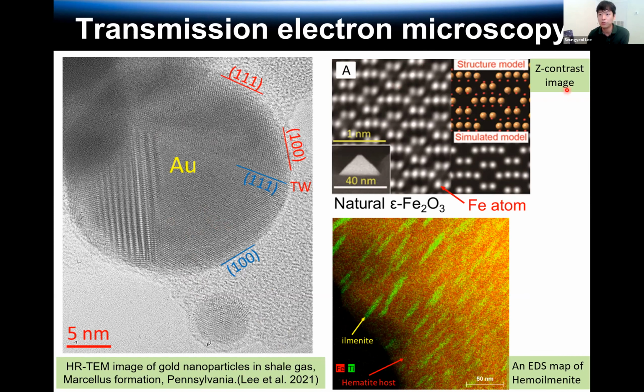Second, this image is a Z contrast image, from aberration-corrected scanning TEM images. Nowadays, the TEM resolution has achieved below sub-angstrom. Sub-angstrom means now we can see the atom positions on the image. Actually, this is iron oxide mineral, and these bright spots are iron atom positions. So now we can directly see the atoms on the image. This is a very powerful tool for characterizing minerals and rocks.